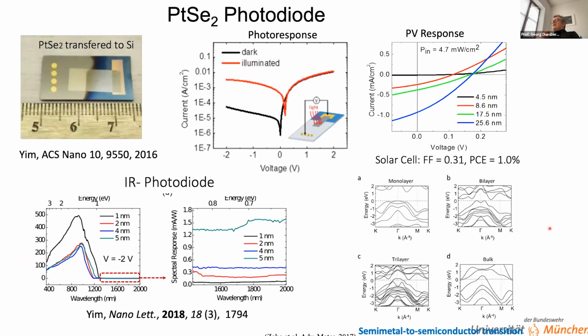Photosensitivity: as I said, this platinum diselenide has a small band gap. It opens up, shown theoretically and also experimentally, for the bilayer and the monolayer. And we would have here in the bilayer something like 0.2 eV, while the monolayer should be about 0.1 to 1.2 eV. We used our polycrystalline films as a very simple photodetector by putting it on silicon. In this structure, having the contact here and a contact region between silicon and platinum diselenide, we actually could sense some responsivity in the IR region as shown here. This would be the silicon region, non-IR, but the platinum diselenide gave us also some sensitivity in the IR region for photo detection.